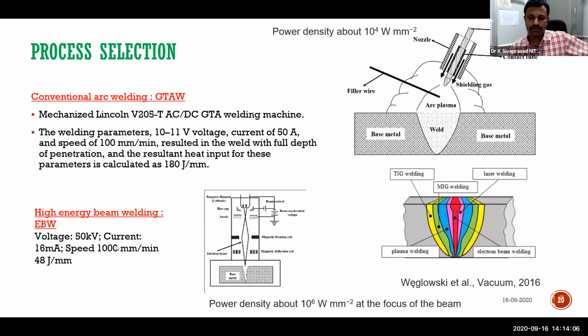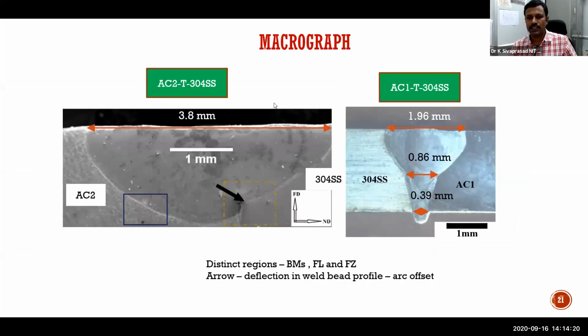So you can see that power density is of the order of 10 power 6 watts per square millimeter, and the TIG welding, similar to that of MIG welding, we have taken, which is power rating equivalent to 10 power 4 watts per square millimeter. So we have taken AC1 to 304 stainless steel and AC2 to 304 stainless steel. One is tungsten, the other one is electron beam. The wine glass shaped fusion joint structure is for electron beam welding.